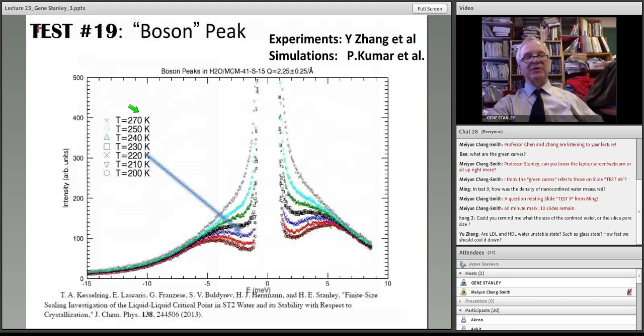We can skip this. And we can probably skip this because these are experiments still underway. But the simulations were done by the same Kumar, who was a graduate student here, finished about 3 years ago, but the paper was just published a few months ago in Nature Scientific Reports. And that was a paper that calculated with simulations the scattering you would expect as you lower the temperature. Let's not worry even about what kind of scattering this is. This is the famous peak, if you will, the Boson peak, and these are the wings of the Boson peak, and they're monotonically decreasing at high temperature. But below the Widom temperature, they're not.